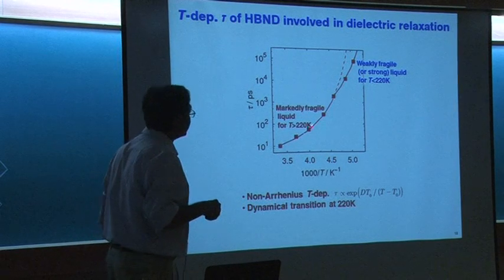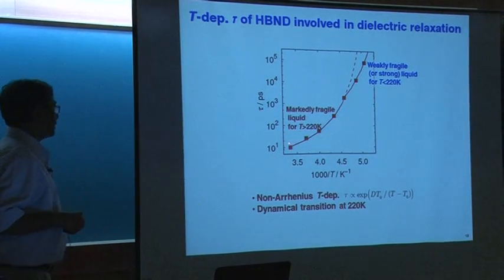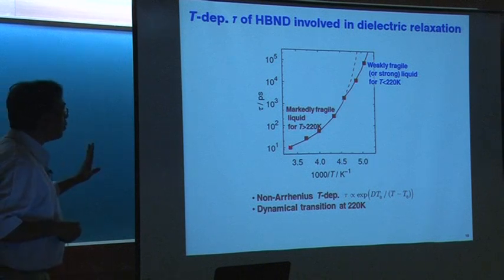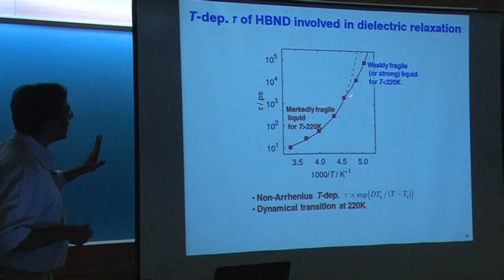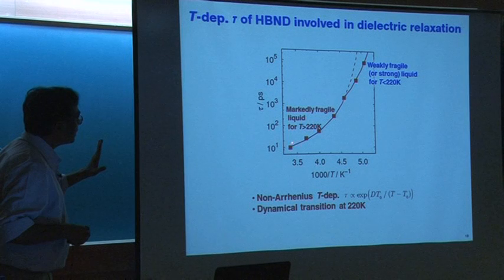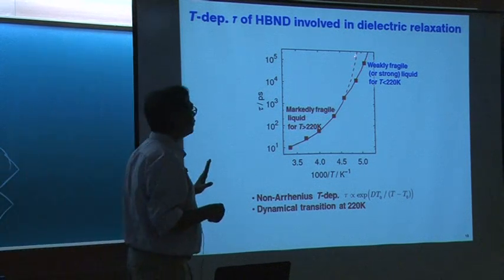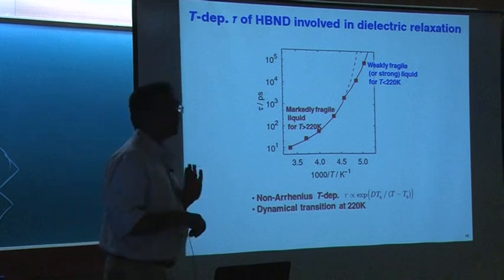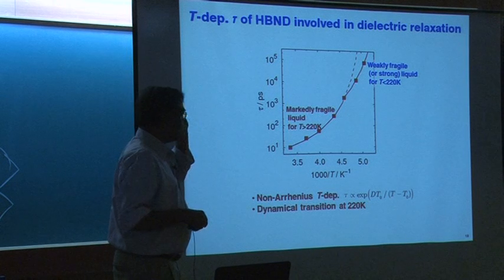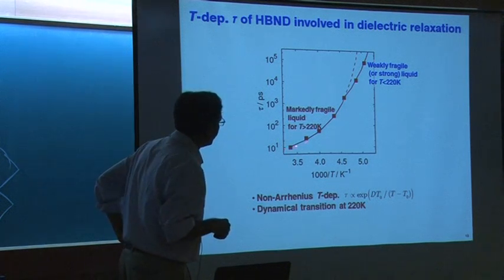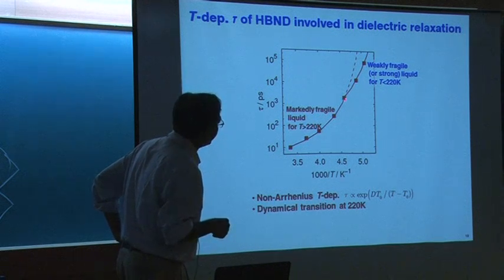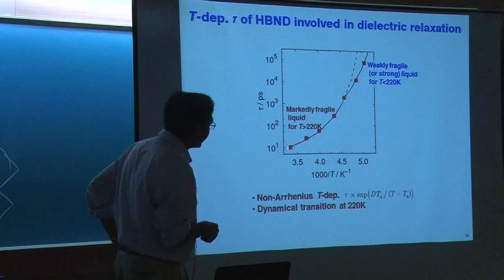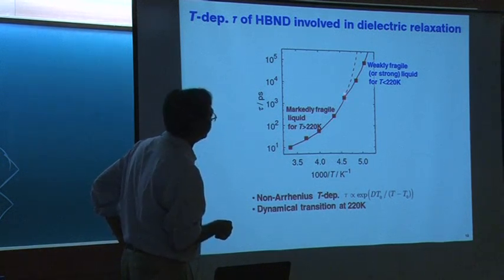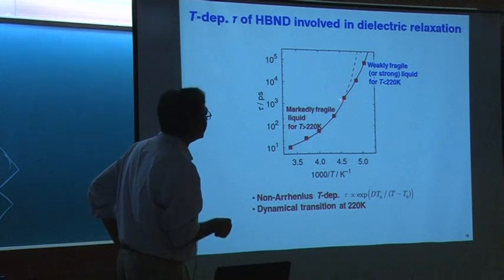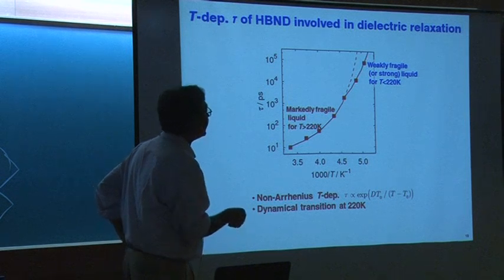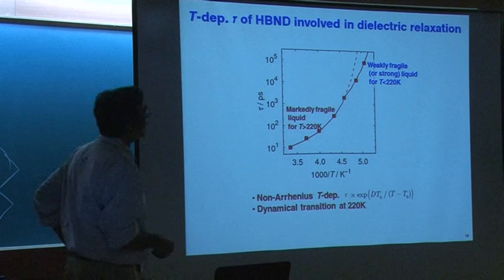Okay. So this region is the region that we know in our ordinary experience of supercooled liquid. Most liquids behave like that. We call them fragile liquids because of the departure from Arrhenius behavior. But most liquids go like that, then they diverge and go over to glass, not water. Water does not go to glass like that. And one more figure I will use very soon. It undergoes multiple transformations, and so 220 Kelvin. This is the water that we drink. That water, continuing like that, would have diverged. But the real water, we believe, undergoes a structural transformation and goes to a different branch. Then it undergoes one more structural transformation before it goes to the amorphous ice state.